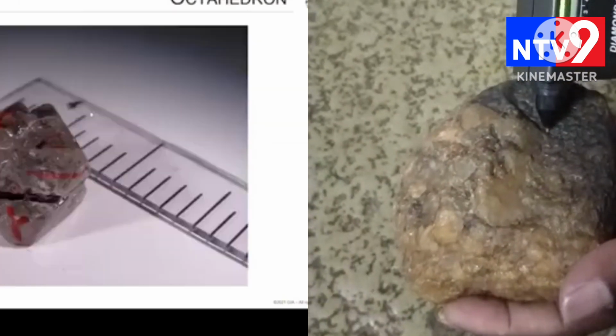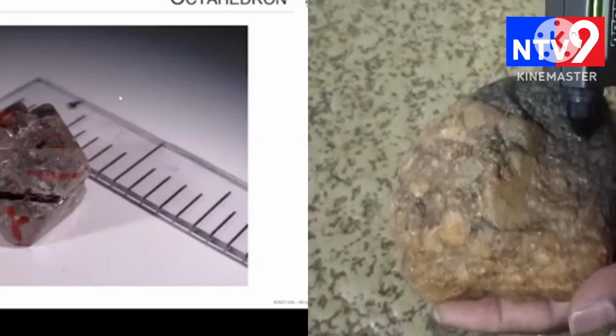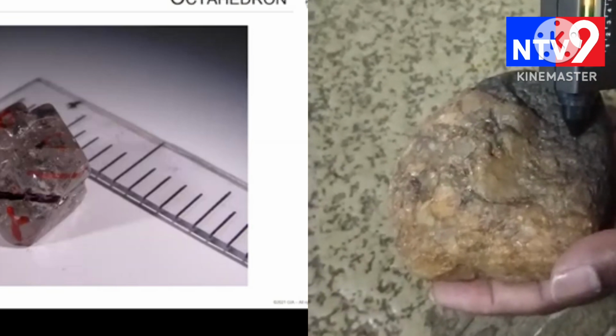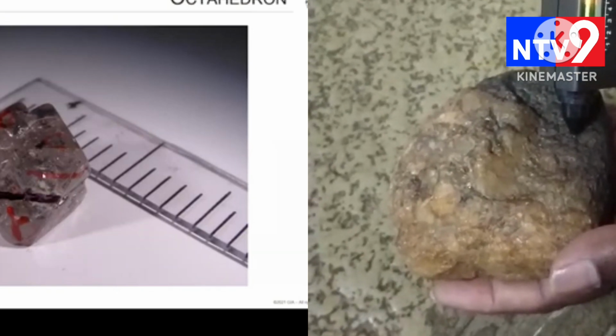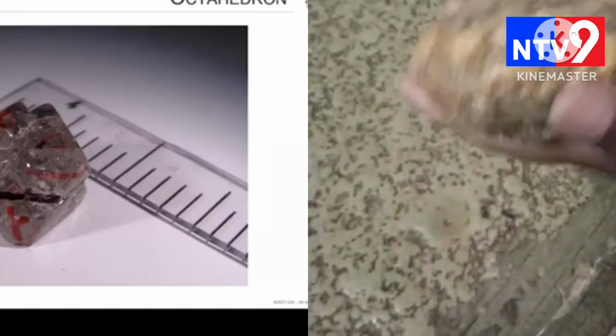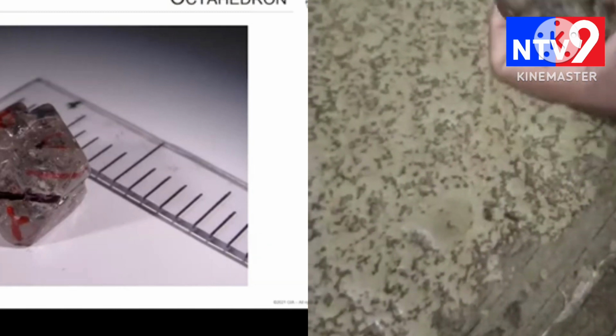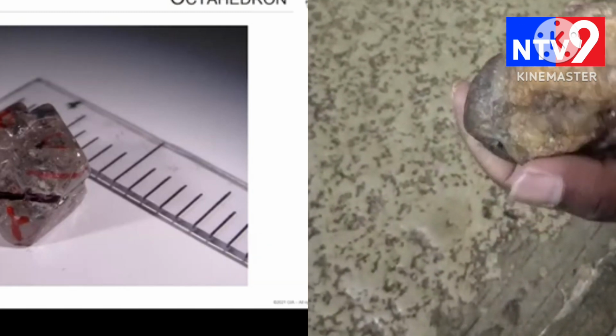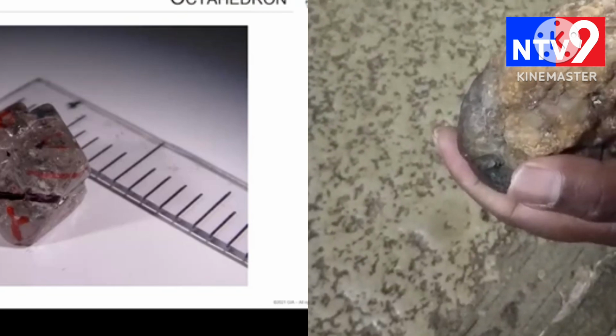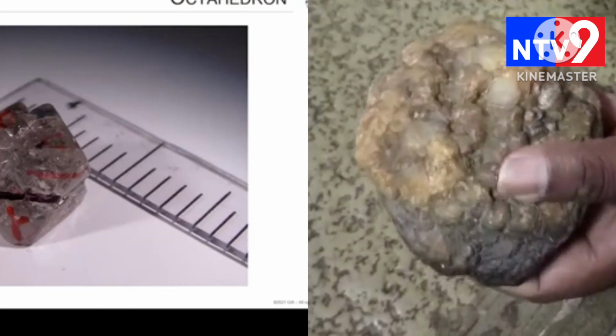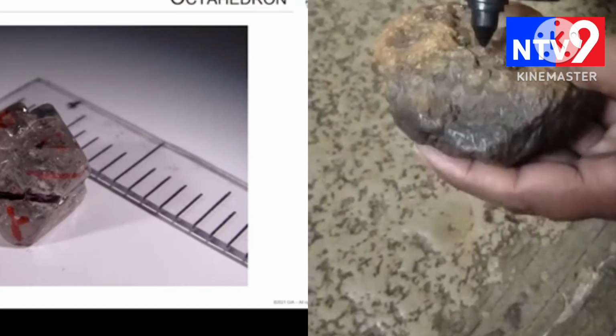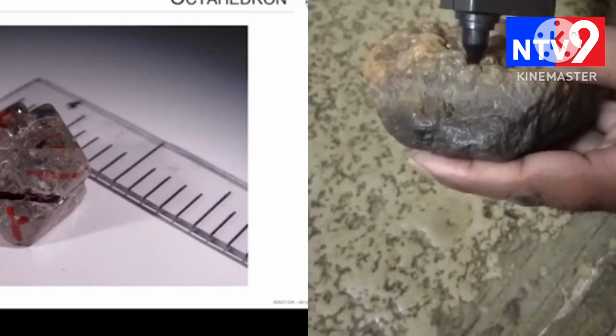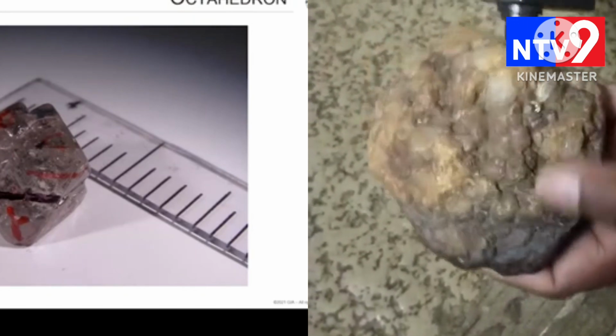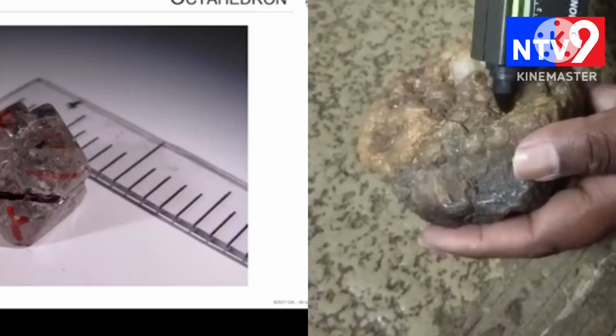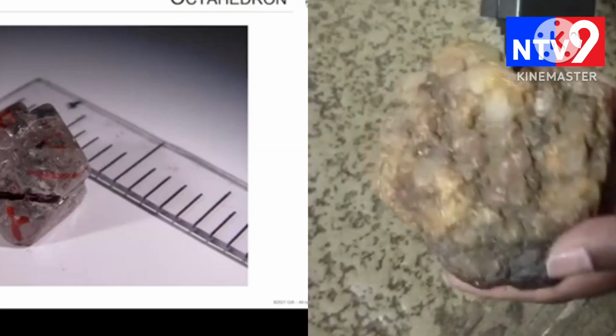So back to the natural diamonds themselves. Here's an octahedron. I've drawn on it, trying to show some of the internal features here, because I was planning to cut it for research purposes. But what I want you to see is that the corners of this octahedron crystal and the edges are a little bit rounded, and this reflects something that happens to octahedral crystals quite often when they're sitting in the mantle or during their volcanic transport up to surface. They get a little bit dissolved or resorbed. So this is something that happens after diamond growth.